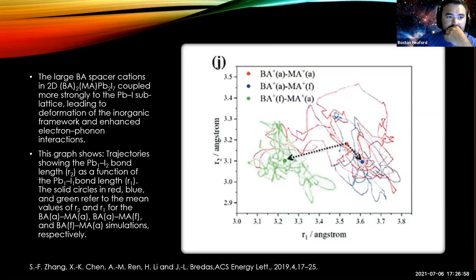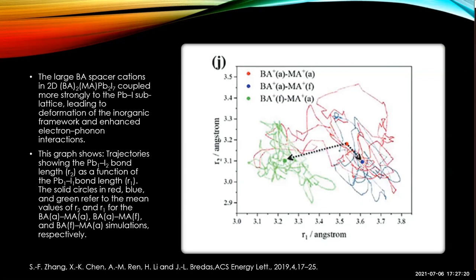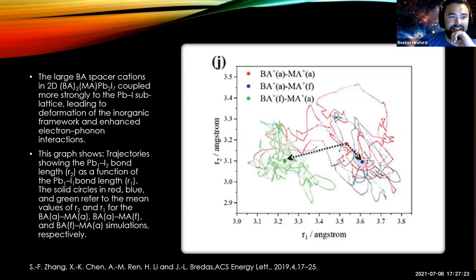And here is a graph showing the spacer cations in the 2D perovskite, and what was it? Remind me again, David, what the BA was. Butyl ammonium. So the butyl ammonium spacer cations coupled more strongly to the lead iodide sublattice, leading to the deformation of the structure, and which enhanced the electron phonon interactions.